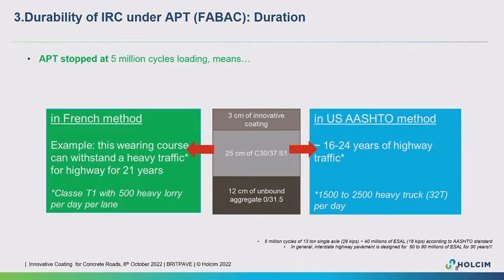And then we run the APT test up to 5 million cycle loading. With this kind of structure, it means around 21 years of traffic T1 in the French category, meaning 500 heavy lorries per day per lane, or if we back-calculate it by AASHTO 93, it's around 16 to 24 years of highway traffic, meaning 1,500 to 2,500 heavy trucks.